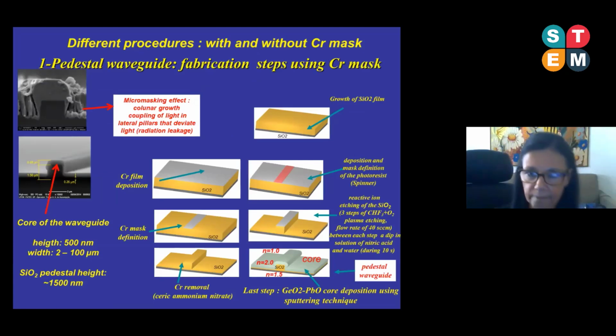We have different procedures to prepare this pedestal waveguide. One of them uses the chromium mask and the other one does not. I will start with the one that uses the chromium mask, and I show you in this slide the several steps used for this fabrication. First of all, we have the growth of the silicon dioxide film, followed by the chrome film deposition and mask definition of the photoresist, chromium mask definition, three steps to etch the silicon dioxide, and finally, the chromium removal. As I said before, the last step is the core deposition.